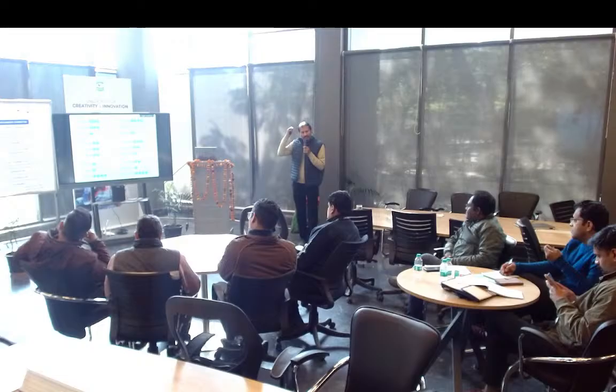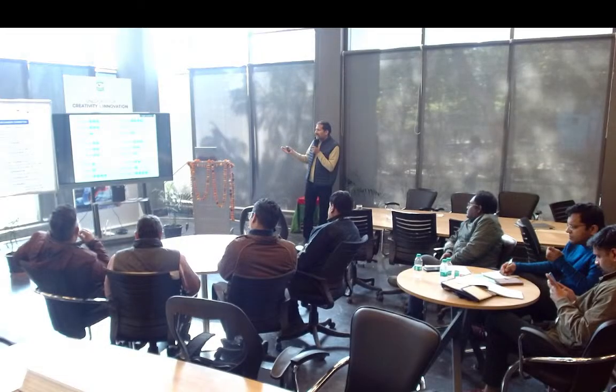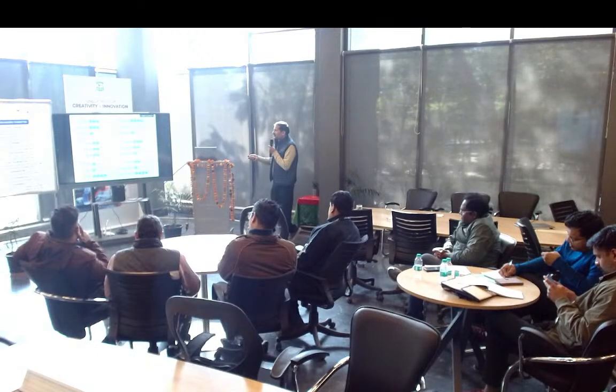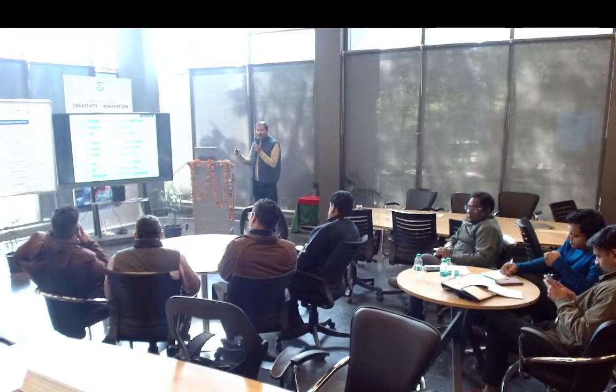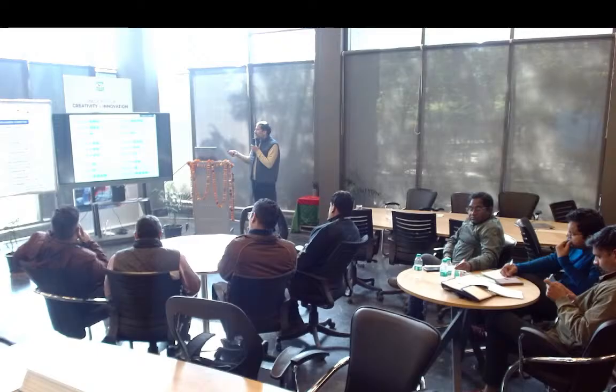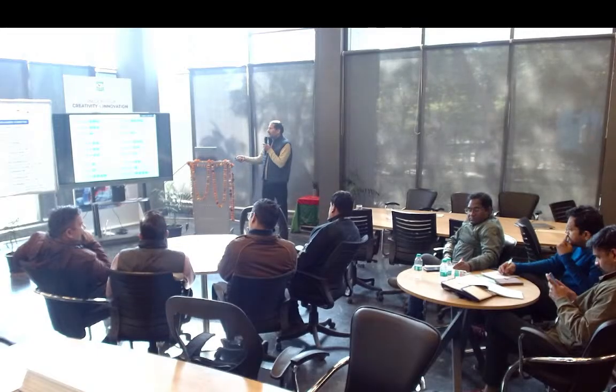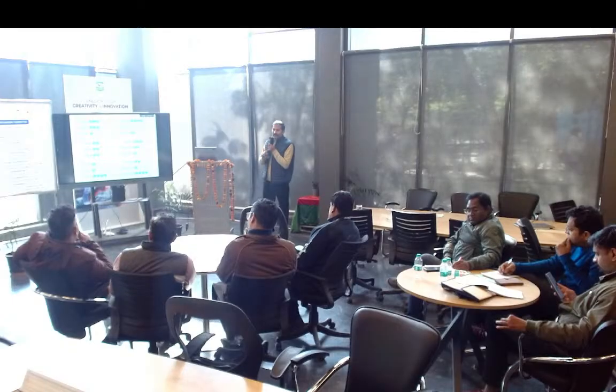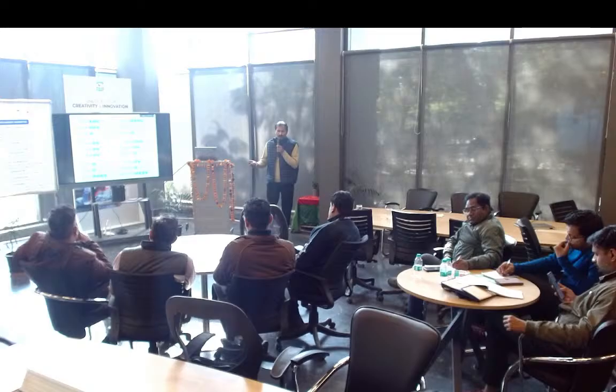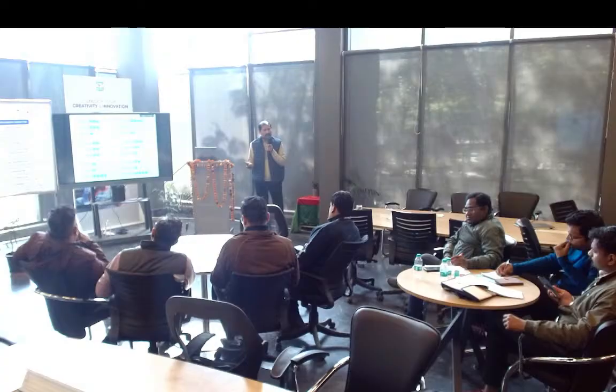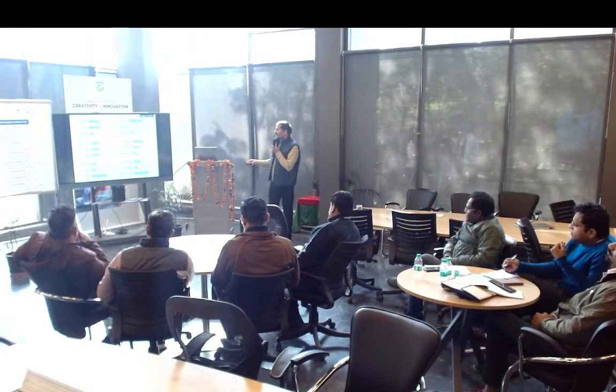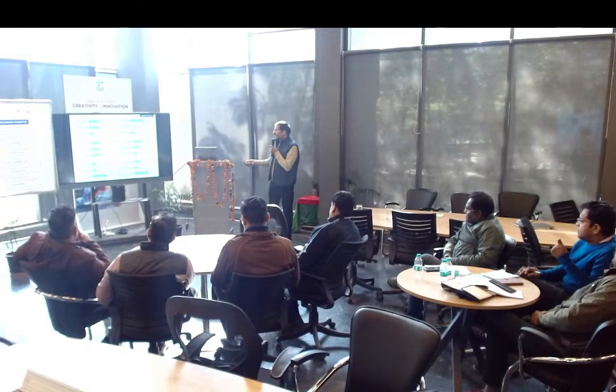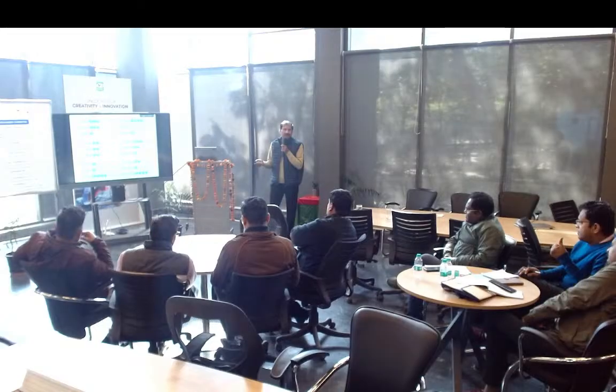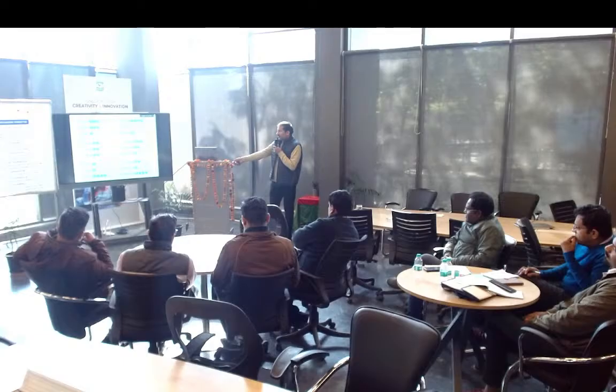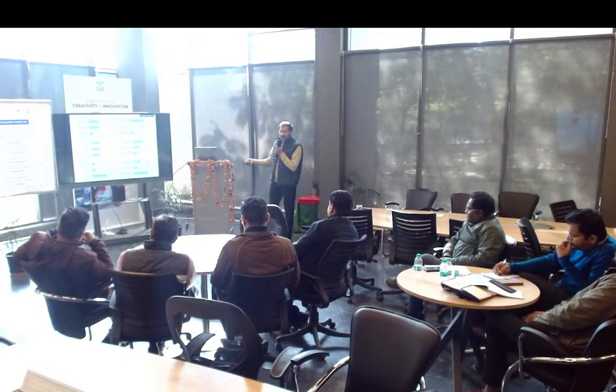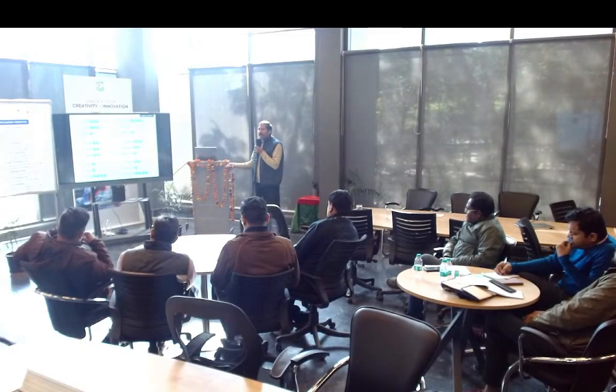So three materials generally used in academia are PLA, ABS and nylon. This is a comparison between the strength, stiffness and durability. PLA has a good strength. It's print friendly. Stiffness is good, but durability is very less. Chemical resistance is less, and it doesn't show any heat resistance. As I told you, its glass transition temperature is 60 degrees, so it can't go beyond that. While ABS, you can say strength is lesser than PLA, but durability and heat resistance are comparatively good. Next is nylon. Nylon is poor on the strength part, tricky to print, but on the same side, durability and chemical resistance are on the high side.